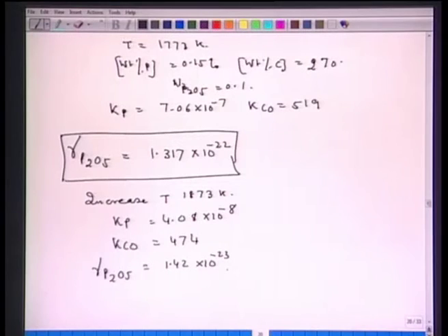That is, if you go for a little higher temperature, the phosphorus reaction may occur, but you still require a very large reduction in the value of gamma P2O5. Therefore, for the simultaneous removal of carbon and phosphorus, one has to see that a slag with a very low value of gamma P2O5 is formed, and then the carbon and phosphorus reactions may be allowed to take place simultaneously such that the carbon removal is slightly delayed as compared to the phosphorus removal. So, that point you should remember. I will be needing it when we go into modern steel making practice.